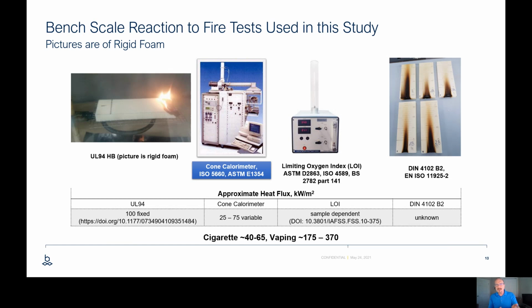I could do a UL94HB, or the MVSS 302, or I could do a cone calorimetry, I could do a limited oxygen index, DIN 4102. It seems that these materials are somewhat used on occasion for each one. We chose to do our reaction to fire testing with the cone calorimetry, just because there's degrees of freedom in terms of adjusting the heat flux to the system. In other words, how much heat is going to the system.